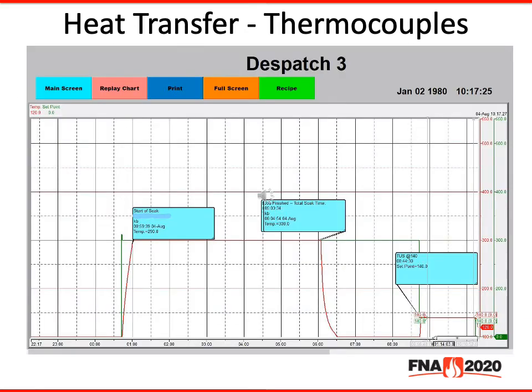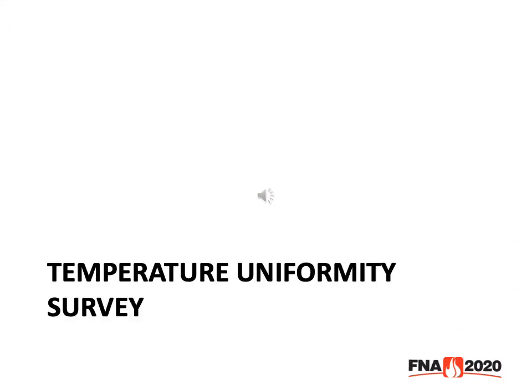If a thermocouple is not reading the correct temperature, a process time may be started long before the part temperature actually reaches the desired point. This would potentially cause the properties of the material to be non-homogeneous throughout. It would be difficult to detect this issue with hardness testing alone. A more destructive form of hardness testing would then be needed. We'll now take a look at temperature uniformity surveys' effect on metallurgy.